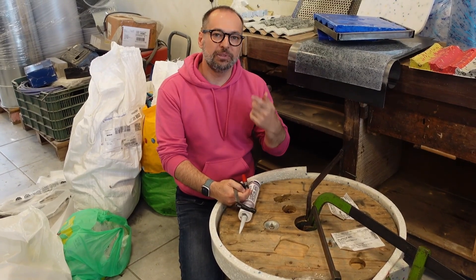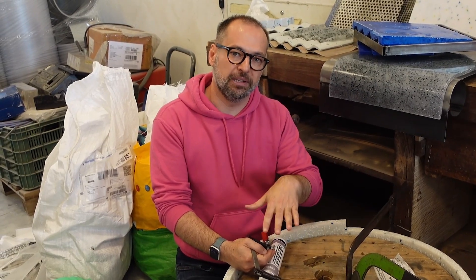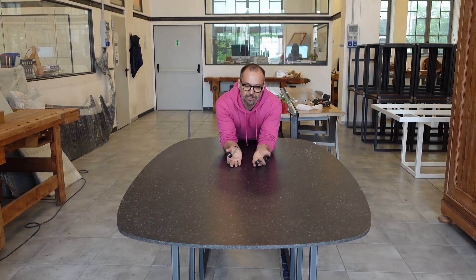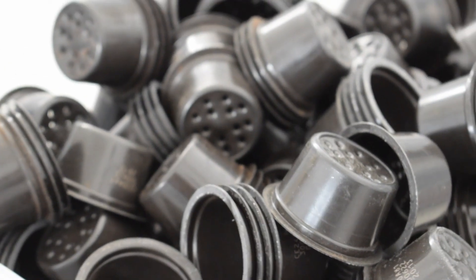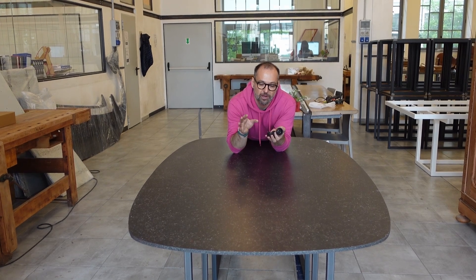Some polymers bend by themselves through gravity — so this is the wrong way to store HDPE. But for the same reason, it's possible to cold-bend HDPE without any heat. Italy — country of saints, wine, but also coffee. This table comes from coffee pods. It's a material that is normally impossible to recycle: it's made by an aluminum cup and the pod is made by LDPE. It's possible to separate them one by one by peeling, but in an industrial way it's impossible to recycle. So we shred everything together and make this.